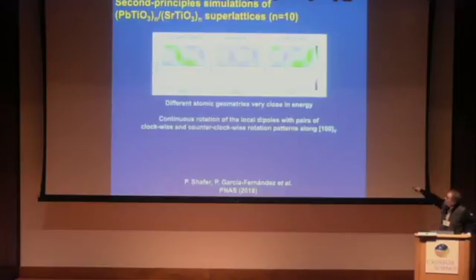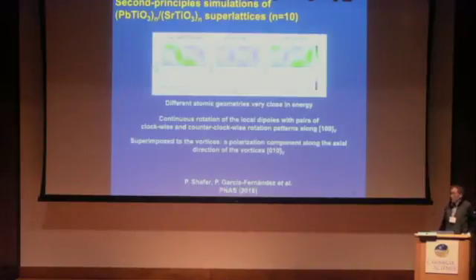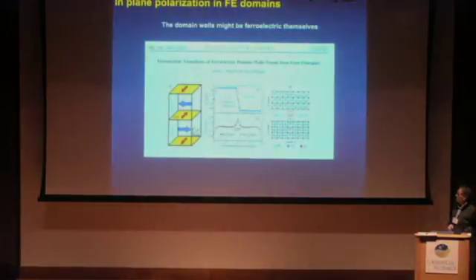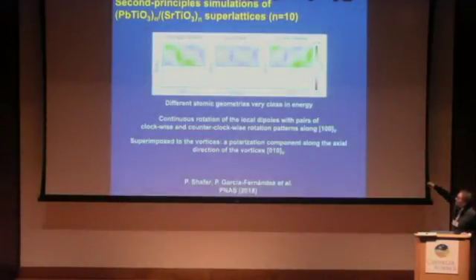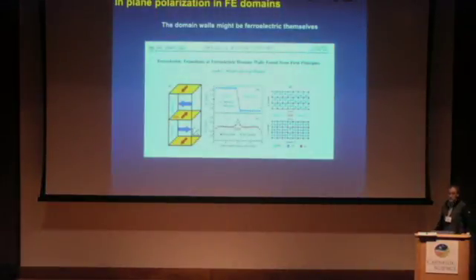So we do observe a continuous rotation of the local dipoles with pairs of clockwise and counterclockwise rotations as before, but superimposed to this structure, we were able to detect a component of the polarization pointing in the perpendicular direction of the screen, so in the direction of the axis of the vortices. So the fact that we have this component of the polarization here at the domain walls suggests that the domain walls themselves are ferroelectric.